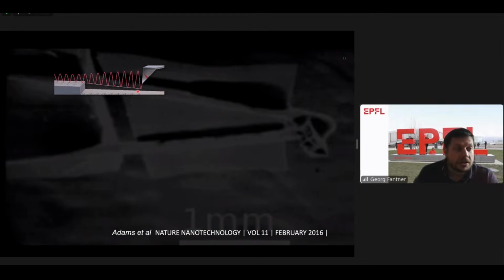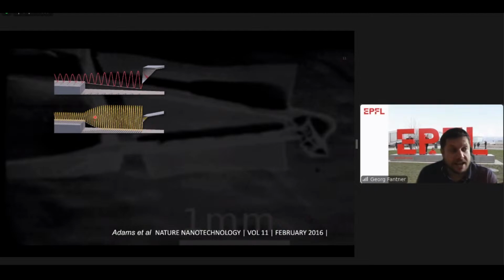That is the easy solution for that. We can just make the cantilever oscillate faster. If you have a higher resonance frequency and it takes the same number of cycles to reach the new steady state, then with this new higher resonance frequency, you will detect the surface faster. And this is the way that most people are working when they're working in high-speed atomic force microscopy: increase the resonance frequency by making the cantilever smaller. The smaller the cantilever, the smaller the mass, and at the same spring constant, the resonance frequency is going to be higher.